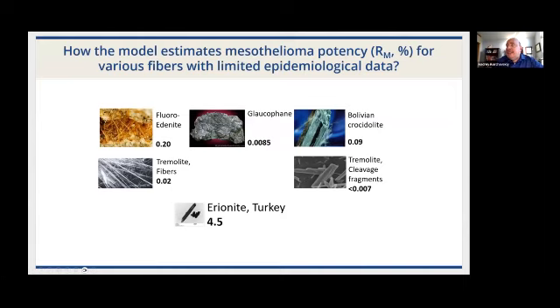Back one step. It's very interesting that our model detects pronouncedly different levels of potency for tremolite being fibrous or asbestiform versus so-called cleavage fragments. Cleavage fragments are small pieces of material of probably the same mineralogical origin, but they're just chunks of the rock, very small and potentially elongate. However, cleavage fragments do not have the same biological activity as true asbestiform fibers. And so this is the difference. We have mesothelioma potency for tremolite. However, cleavage fragments show less than 0.007.